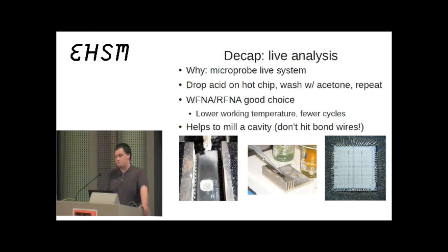Typically, a dropper is a good choice to dispense it, and you run this on a hot plate, put a few drops on, then wash it in acetone. I'd also give a little more caution with that. If you just flat out combine fuming nitric acid and acetone, it will probably explode. But typically, by the time you've let it sit on the chip for a little bit, it's more or less neutral. So if you wash it in acetone, you'll have a very minor reaction, but not enough to be dangerous.